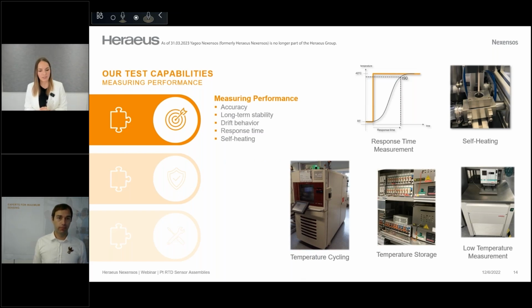All right, so here you can see the test capabilities of the measuring performance. Belonging to the measuring performance, of course, is the accuracy, the long-term stability, and the drift behavior of the sensor assembly. And on the bottom, you can see three test setups that align to those measuring performance aspects. A very standard test setup is the temperature cycling test. For example, the sensor assembly would be exposed to temperature cycling from -50 to 150 degrees Celsius 1,000 times. And then we have the temperature storage test.